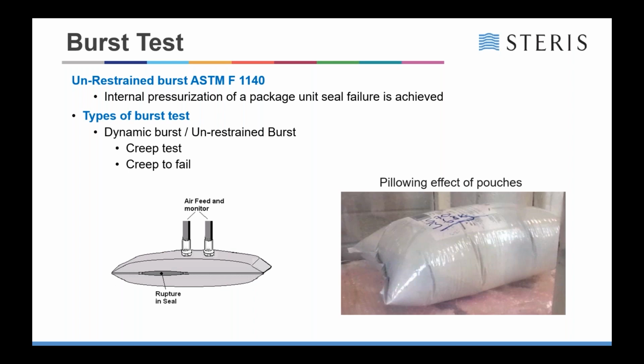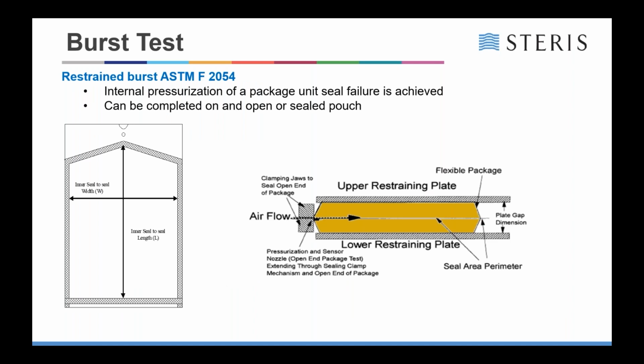If we look at the other version of the test, which comes under ASTM F2054, it's a restrained test. What that does is significantly reduce the pillowing effect of the pouch, and virtually eliminates those strain areas or stress areas on the actual seal, and you have a much better chance of detecting a weak seal.